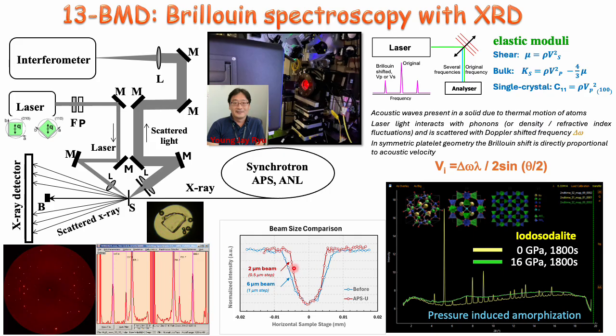And just after the recent upgrade, we have significantly reduced the focal spot in the horizontal direction. Before it was 6 micron, now we can get a 2 micron beam size, and just yesterday we were able to focus the beam down to less than 1.5 micron. And here is an example of the data that we first collected after the APS upgrade. We can see amorphization of the sample and the diffuse scattering is very well visible.